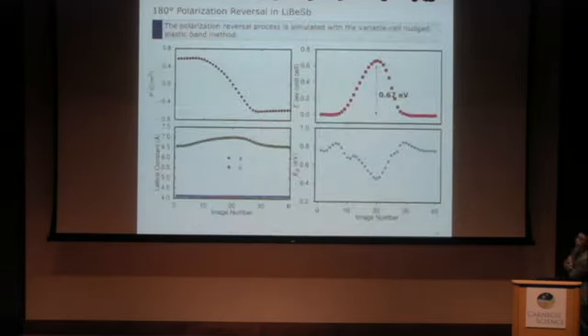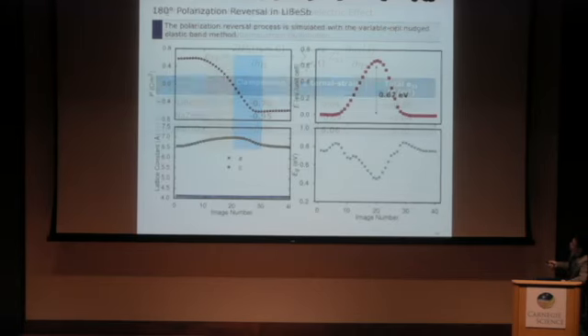We further look at the polarization reversal process in this compound with the variable cell nudged elastic band method. What I show here is the polarization reversal, the switching barrier, for the zero field case. So the barrier is high, as we would expect from the very high barrier in the double well potential. And through the switching, the structure remains insulating. If you look at this intermediate region, when the polarization becomes smaller, the c-axis actually becomes larger. And when the magnitude of the polarization becomes larger, the c-axis shrinks, contracts. So again, all different computational methods are consistent with each other, really demonstrating the presence of a negative longitudinal piezoelectric effect.